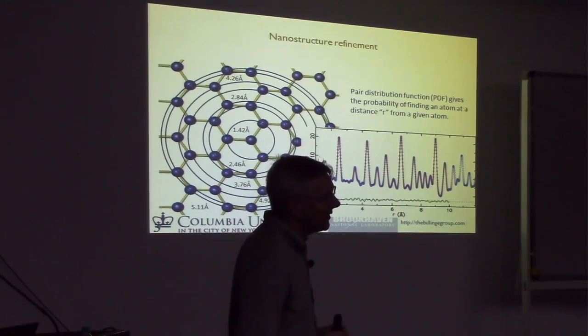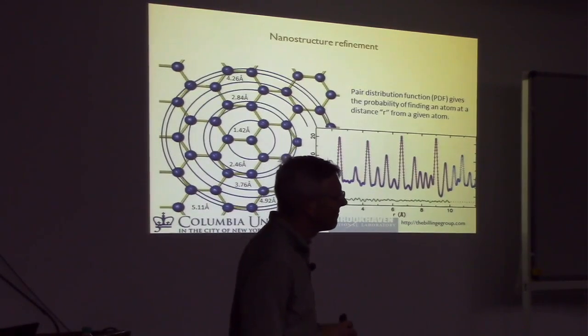Yeah, I mean it's basically a sampling thing, so the resolution in real space is something like 2 pi over Q max. I'm not sure if that's the exact relation, there may be a more exact one, like 5 pi or something, but that's the rule of thumb. So that's all.